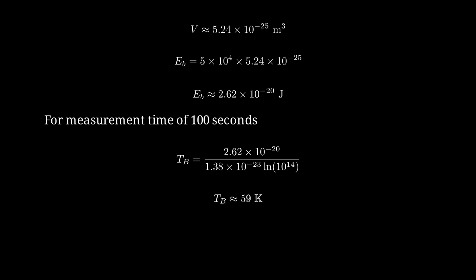If our measurement time is 100 seconds, we can calculate the blocking temperature. TB equals 2.62 times 10 to the negative 20 divided by 1.38 times 10 to the negative 23 times the natural log of 10 to the 14th. This gives us a blocking temperature of approximately 59 Kelvin.